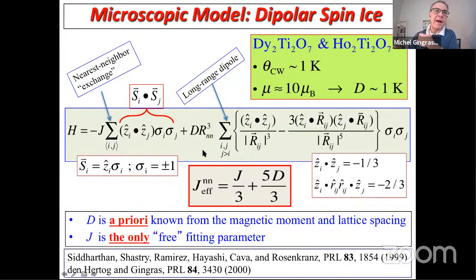And this model is supplemented by a nearest neighbor term, which is also Ising-like, but it's a peculiar Ising term. It's not the Ising direction. Again, these are the diagonals of the cube, these vectors that pierce in and out of the tetrahedra. And so the Ising directions, which are denoted here by z_i, point locally along the cubic 111 directions, the four of them. If you combine these two terms together and you only calculate the dipole interactions at the nearest neighbor and combine them with the nearest neighbor exchange-like term, you get an estimate of the nearest neighbor energy scale, which is given by this formula in the red box here, J over 3 plus 5D over 3.